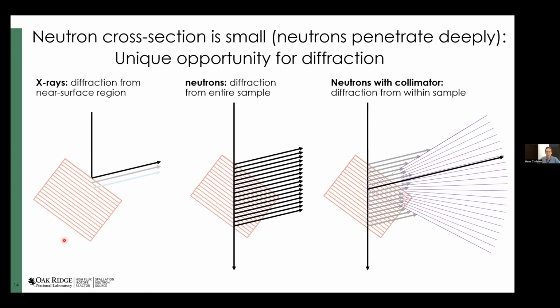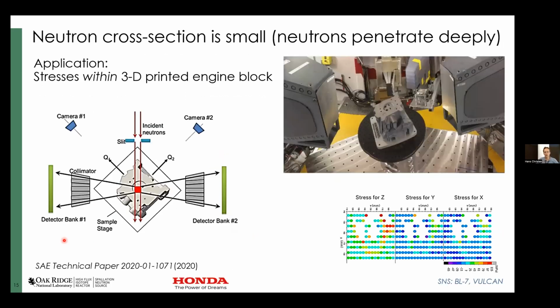And with that, here in the photograph on the right, you have a 3D printed engine component made by Honda of a very novel alloy. And the question is, what kind of mechanical stresses are built up during this 3D printing process? It's really hard to figure that out, because if you cut it apart to look at it, the stresses are no longer there. So you have to have a technique where you can measure the stresses inside the component, and neutron diffraction allows you to do just that. That helps you then to design the process for 3D printing of these materials.